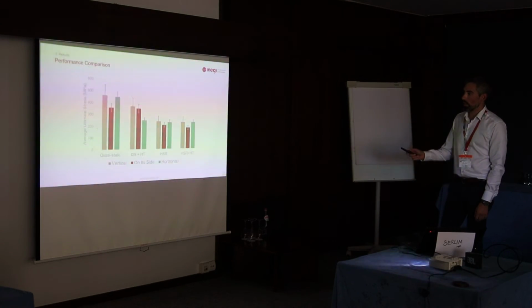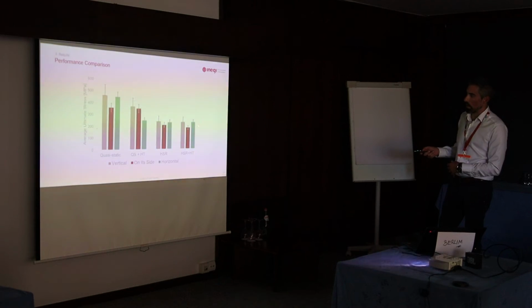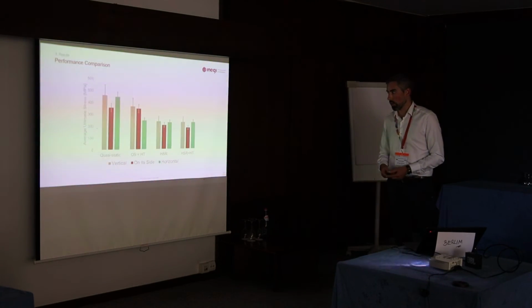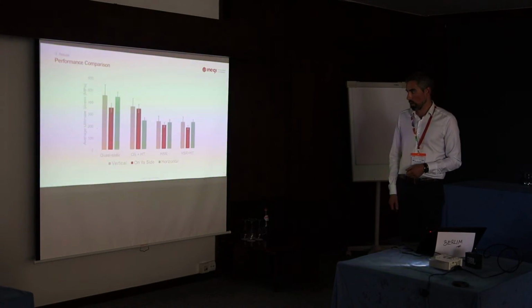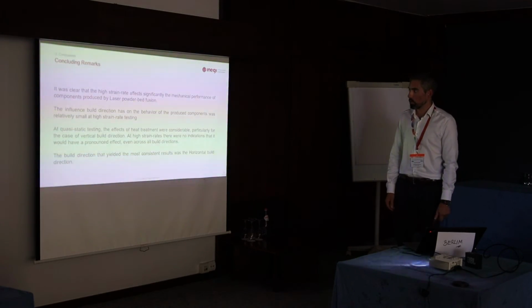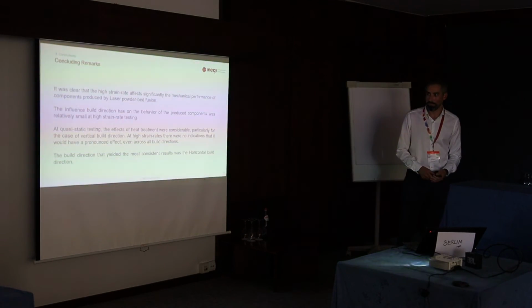And just to finish the comparison with all the heat treatment, the quasi-static and the high strain rate. For the high strain rate, the three conditions of fabrication were very similar. But in the case of the quasi-static strain rate is where we would see the post-heat treatment effect and the variations with the direction of build. And I conclude my presentation. Thank you very much.